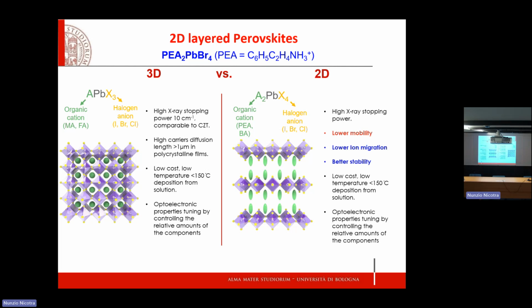Just to go quickly to another way of exploiting thin films: going to 3D versus 2D perovskites. If you change the dimensionality of your film and don't go for 3D perovskites, but go for 2D perovskites, you can take advantage of some of the features of 2D materials. 2D perovskites have a lower mobility, but a much lower ion migration. And ion migration is one of the killing effects that is presently blocking perovskite from being widely exploited, even in solar cell applications.